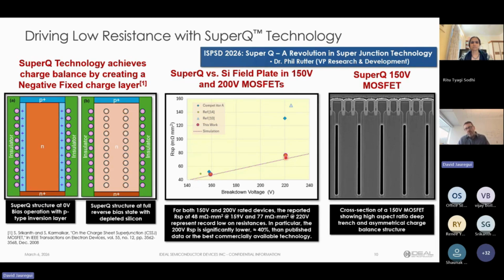But then if you look at 200 volts, that's where our separation really starts to get greater. This first generation platform that we've developed was really more intended for 200 volts and greater. Our next generation platform is going to build on this and then hopefully put a larger leadership position. But you can see that resistance per unit area separation gets greater at 200 volts. That gets significantly greater at 300 volts, 400 volts, and then better at 600 volts.